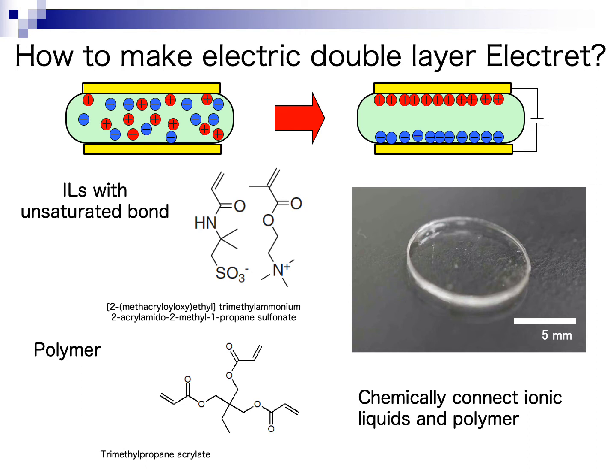After we apply the voltage, the electric double layer is formed. And then we shine UV light to polymerize these materials, and the ions are fixed inside the polymer network. And so far, more than 99% of the ions are fixed inside the polymer network.